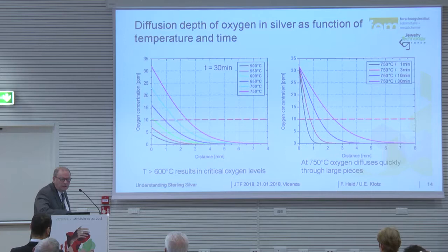Here we have the diffusion depth of oxygen in silver as a function of temperature and time. Here is the oxygen concentration against distance at different temperatures. You see our 10 ppm line for measurement. The higher the temperature, the higher the oxygen concentration. In another picture, you can see oxygen concentration in ppm and the distance oxygen can move during annealing. If we look at 750 degrees, 1 minute here, and then 30 minutes, it can travel up to 2.5 millimeters.